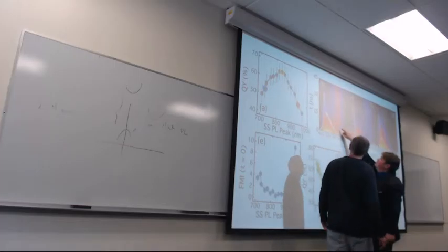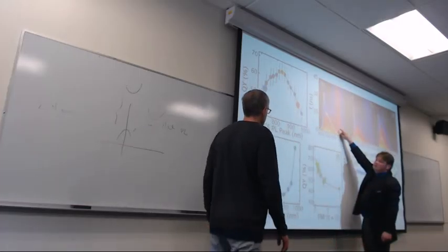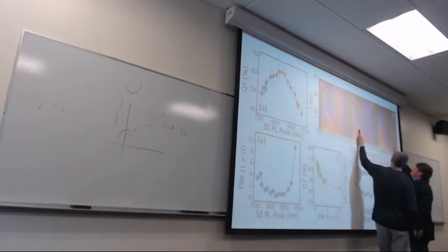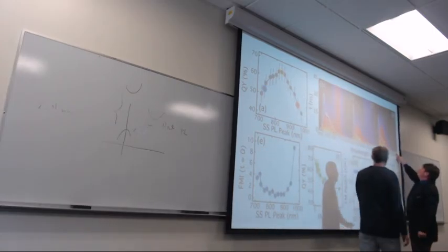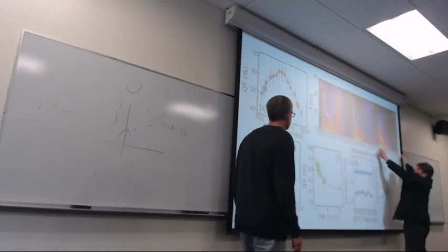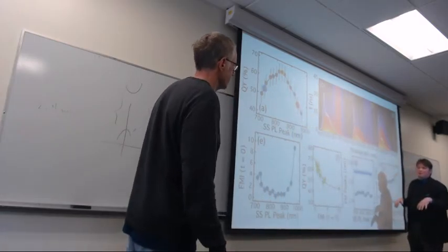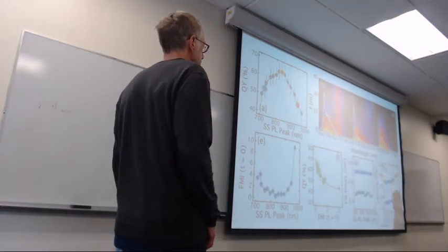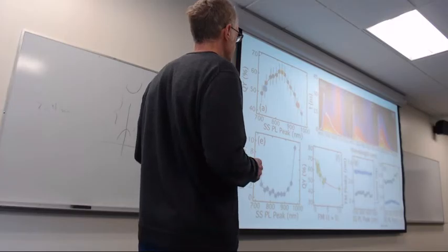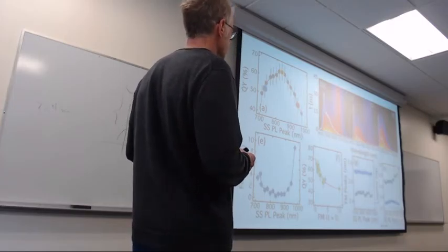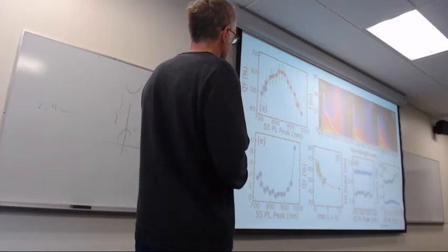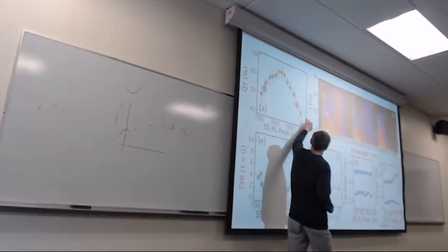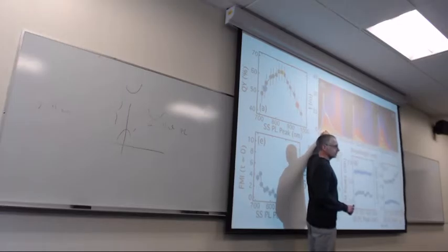And as soon as you get them bigger, the band gap emission disappears. It moves to the red, just like you'd expect. It goes off scale, but it still exists. So it doesn't quench because we go to the bulk regime? No. This is all well below the bulk. What's killing the quantum yield on this end and this end is whatever is giving you this relaxation.